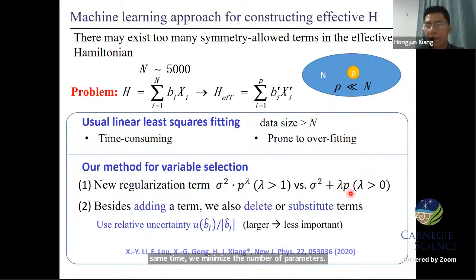However, we found that this widely used regularization term is hard to use, because for different kinds of systems, the lambda parameter is hard to choose. But if we use a new regularization term like this, sigma square multiplied by this term, we found that the lambda parameter is around 1.0 to 1.1. So it is easy to choose the lambda parameter.